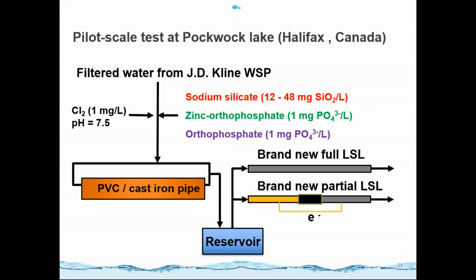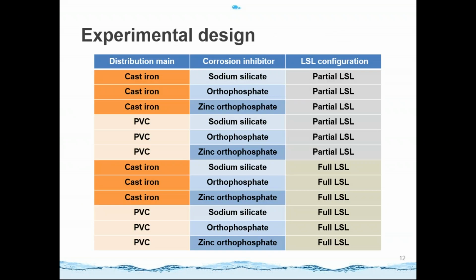Then the water goes through a pipe loop system, which is made of PVC pipe or recovered cast iron pipe. Then the effluent of the pipe loops goes into the reservoir. Then we pump the water from the reservoir into one brand new full lead service line pipe and a brand new partial lead service line pipe. And the water will be stagnant for 24 hours before sampling. So this is our experiment setup.